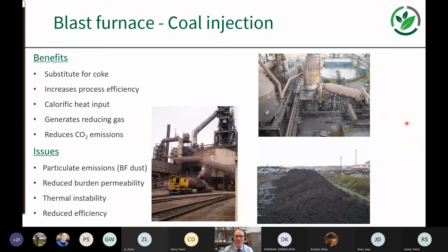And the benefit of using this is it substitutes a portion of the coke. And coke is produced by heating coal in an inert atmosphere, and it requires a lot of pre-processing. There's a lot of emissions associated with it. It's one of those things that you try to minimize, really. So coal injection improves this process efficiency, raises the heat, generates a reducing gas, and consequently, by improving the yield, it reduces CO2 emissions. But there are potential issues from it because of particulate emissions, which then hinder the gas permeability through that burden of raw materials, which I explained earlier in the countercurrent reactor.